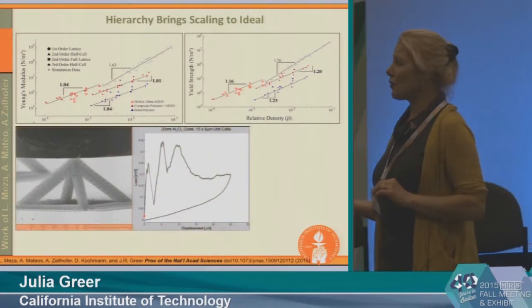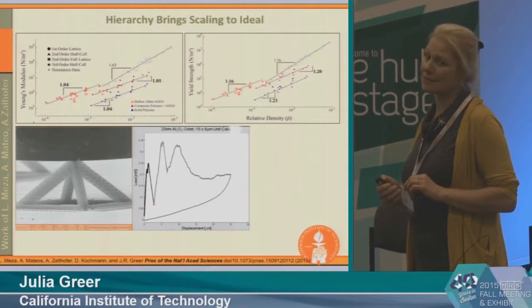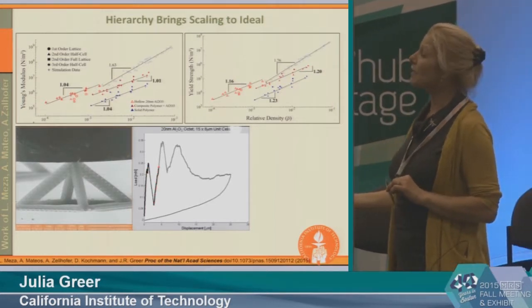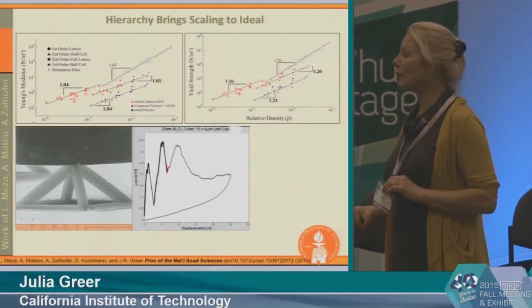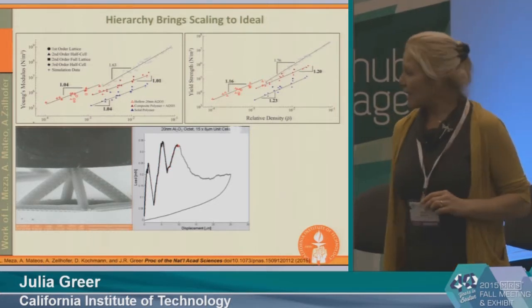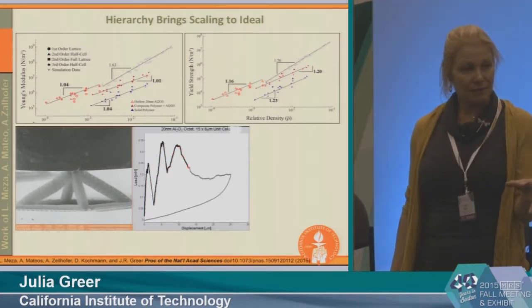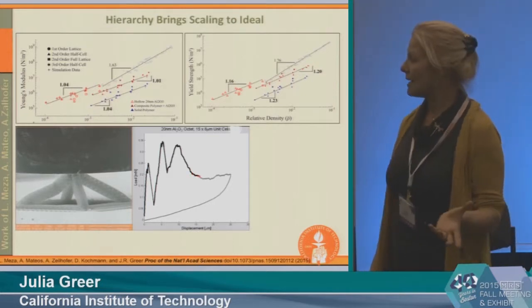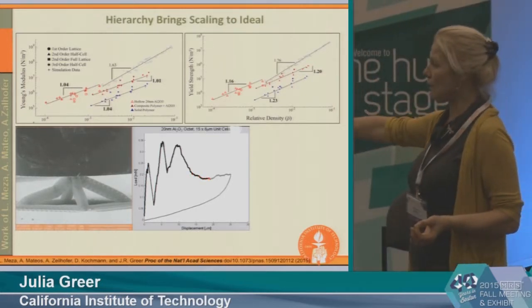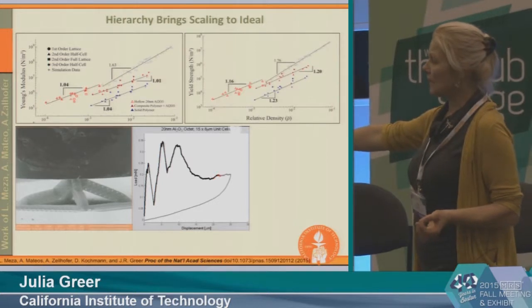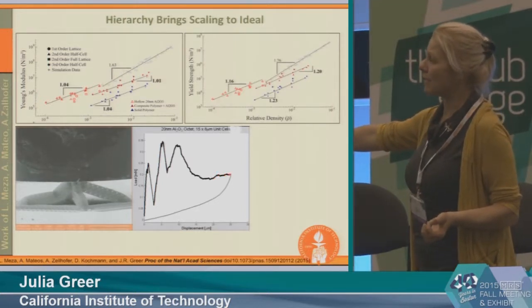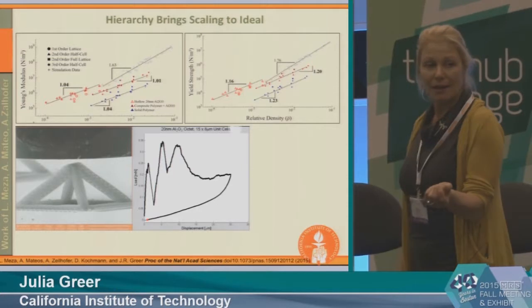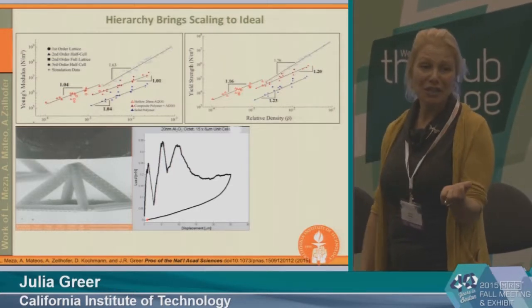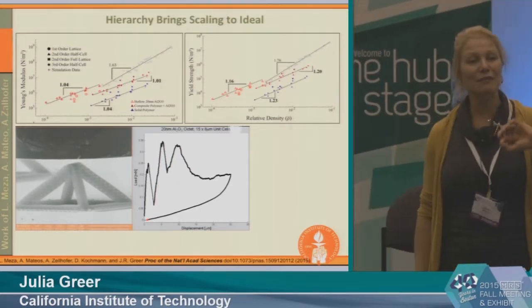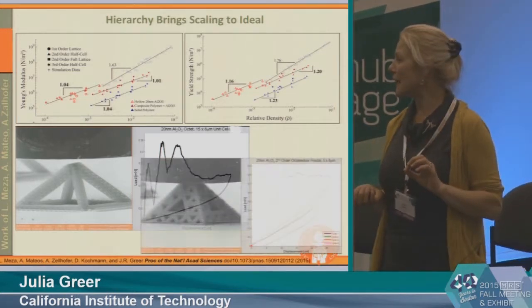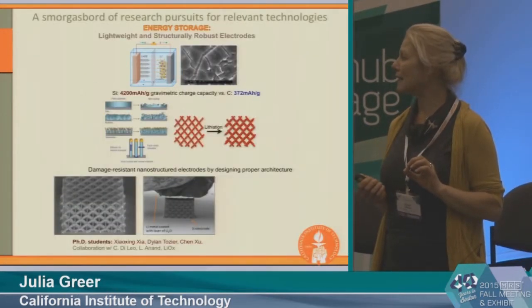The video I wanted to show you is one of these hierarchical nanolattices, and we're going to compress it. And so here's the pointy top. We collapse the pointy top first, and then we start kinking these. Yet again, this is a brittle ceramic, which we're expecting to break at any point now. You can see the kinking, very pronounced kinking right here in this beam. And as it's kinking, this is exactly where it's going to snap, probably here and here, right? This is a ceramic. And what you see is that it fully recovers. So by introducing these different levels of hierarchy, we can really study their behavior in much more complicated geometries.